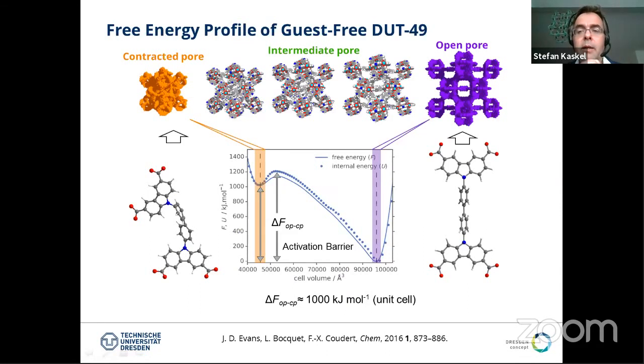So what's the mechanism behind? And this comes a little bit also to the question of the adsorption enthalpy. And here, the power of in silico prediction and design is very important. For example, here by the work by Jack Evans and FX Coudert in 2016, these materials have a typical bistable behavior. They have a global minimum. This is the cell volume at the large open cell in the OP structure when there's no guest, meaning that this stretched form of the linker is the thermodynamically stable form. But there's also a local minimum when you compress them, when the linker is buckled. It's basically the compressed or tilted form of the linker here in this case, which is energetically much higher. So here they calculated 1,000 kilojoule per mole per unit cell. So this is the bistable profile, and this is typical and a prerequisite for this type of behavior.